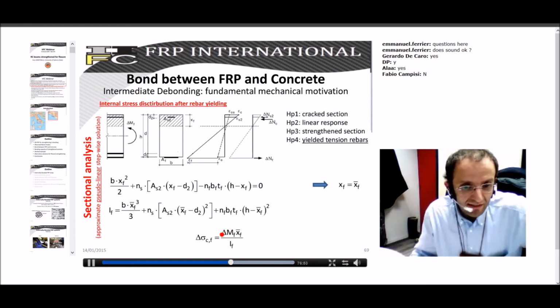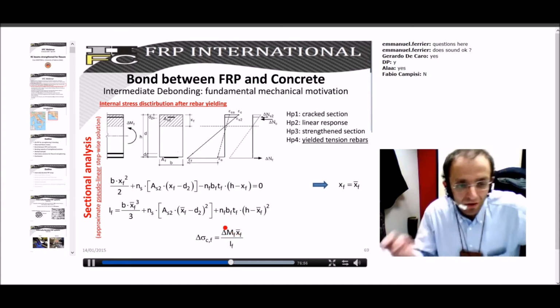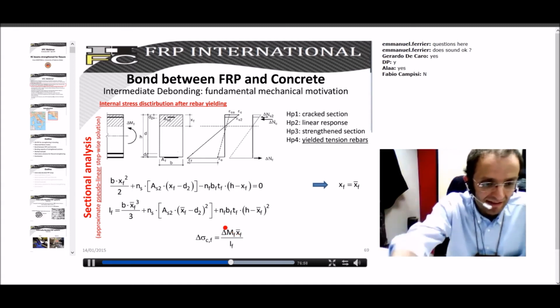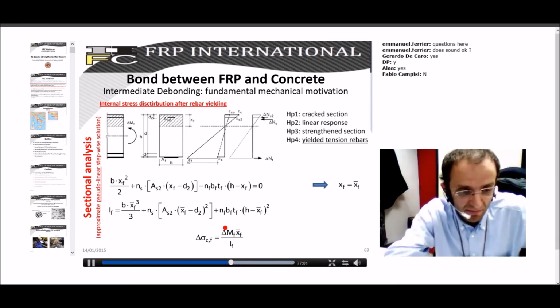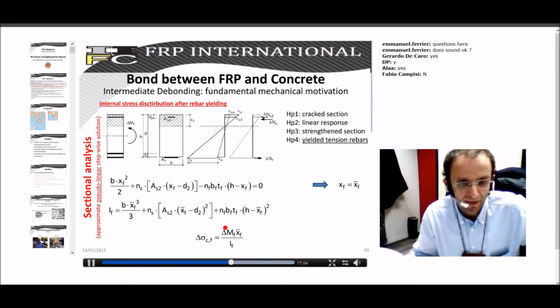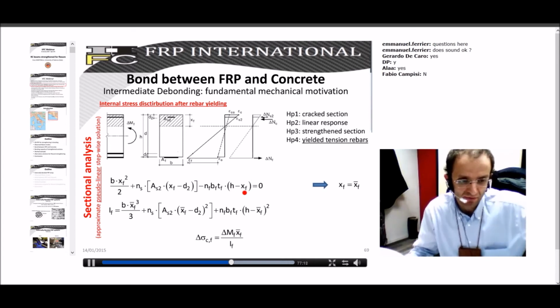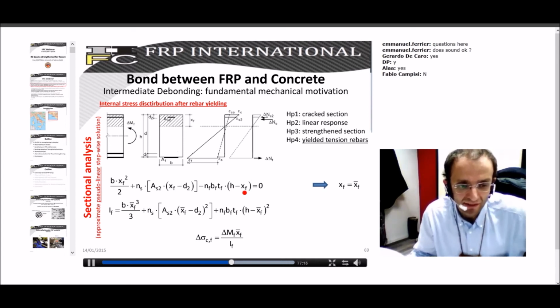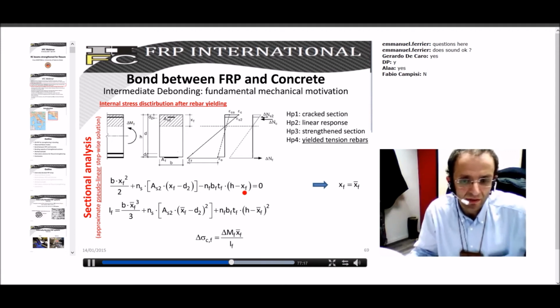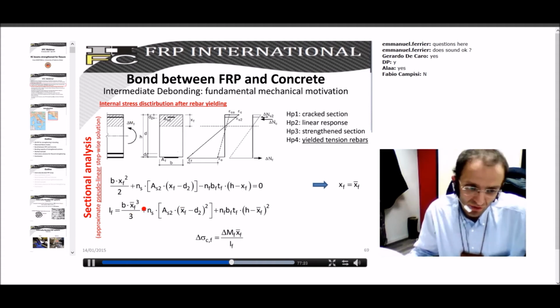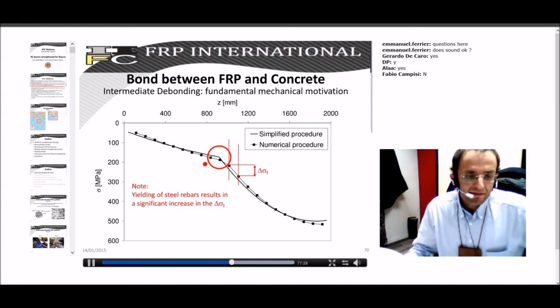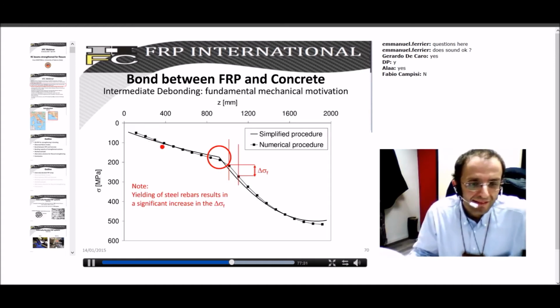That's why delta m is indicated here as delta m f, because it only increases the delta sigma in the fibers, not in the strip, not in the internal part. It can be evaluated with the same technique. You can evaluate a new position for the neutral axis, which only applies for the increase of the moment after the yielding of the internal reinforcement, and this means that you can evaluate also your internal moment and the increment in terms of delta sigma. And this is how this delta sigma looks like.